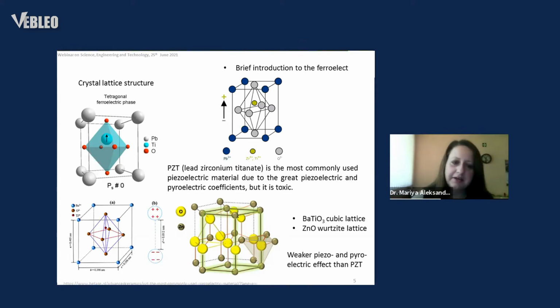So these piezo, pyro, or ferroelectric effects are possible only for non-central symmetric structures or lattices that should be polar in addition. It means that the crystals have no mirror plane and have no two-fold axis perpendicular to them. The most commonly used material in this case is lead zirconium titanate. It exhibits the strongest piezoelectric modulus and pyroelectric coefficients, but unfortunately it has been considered toxic in recent years.